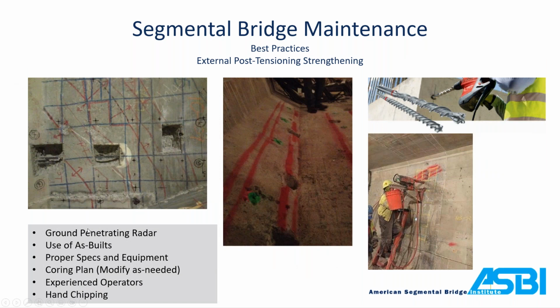Some lessons learned from that project: ground penetrating radar can be very accurate or it can be really sloppy. It depends on the firm. Luckily we had just gotten off a previous segmental bridge project where we had a really good ground penetrating radar contractor that was right on the money with their locates of their tendons and critical reinforcing steel. So when we got to Muskegon, the first GPR contractor was out there and they whipped through it. Took about a day for them to mark everything off, and they were off plus or minus 1.5 inches, 2 inches, which is too far for us because we were splitting hairs, coring through bars with 3-inch spacing. So plus or minus 2 wasn't going to cut it. So we had another contractor come in and they dialed it in and got us right on the money.